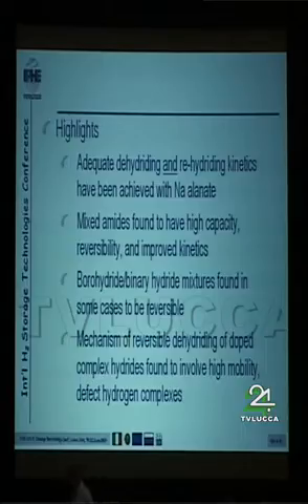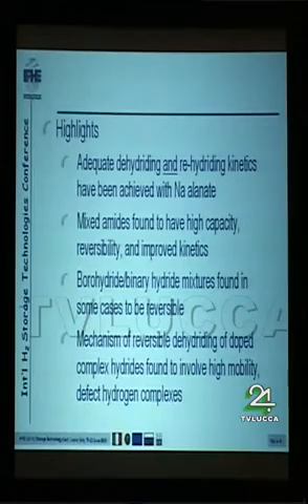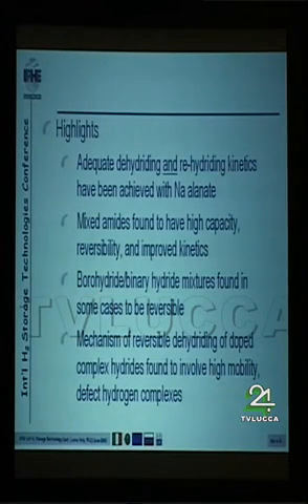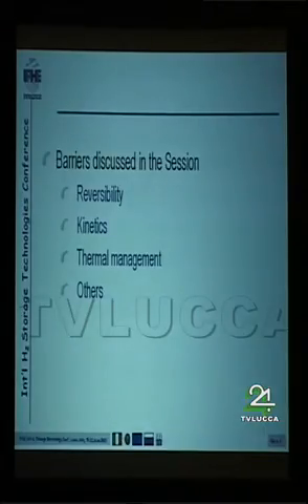Highlights: adequate dehydriding and rehydriding kinetics have been achieved with sodium alanate. Mixed amides found to have high capacity, reversibility, and improved kinetics. Borohydride binary hydride mixtures found in some cases to be reversible. Mechanism of reversible dehydriding of doped complex hydride found to involve high mobility defect hydrogen complexes. Barriers discussed: reversibility, kinetics, thermal management, and others.